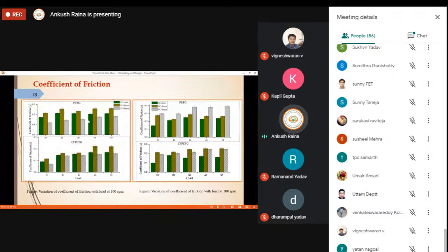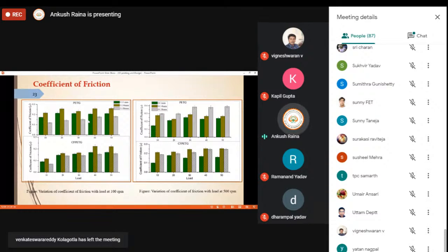The carbon reinforcements add strength to the polymer matrix. The real area of contact with the counter body under load is reduced. As I told you, what is the apparent area of contact and the real area of contact. So the real area of contact has an important role to play in tribological applications. Due to the reduction in this true contact area, the layer thickness did not affect the coefficient of friction at different loads for carbon reinforced PETG. Also, as I told you, the film formation capability, which I will show in the SEM analysis we have carried out in the coming slides. The film formation capability of the carbon fiber further aided in reduction of the coefficient of friction even at these high speeds.